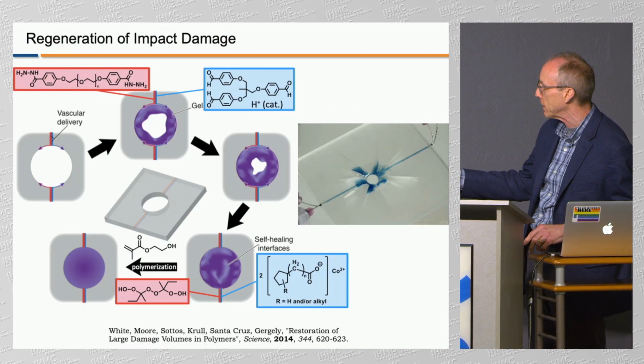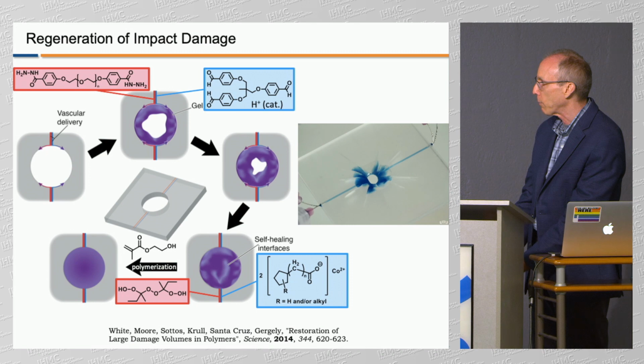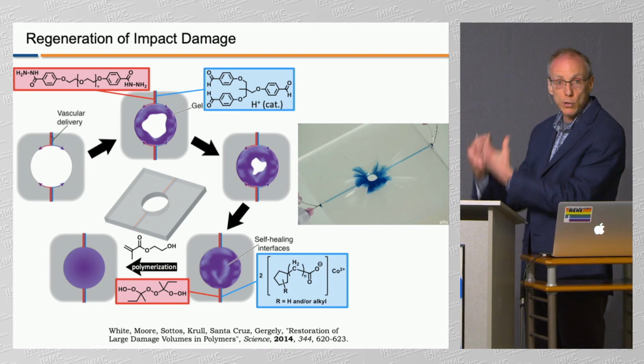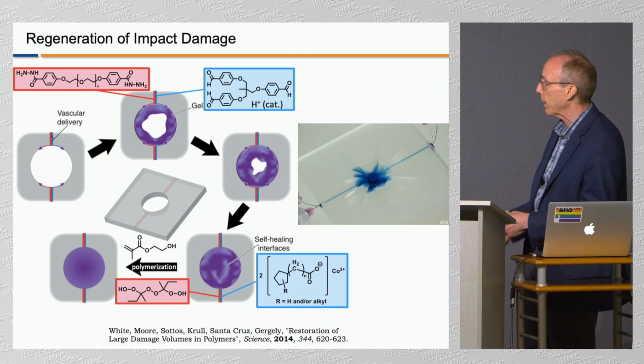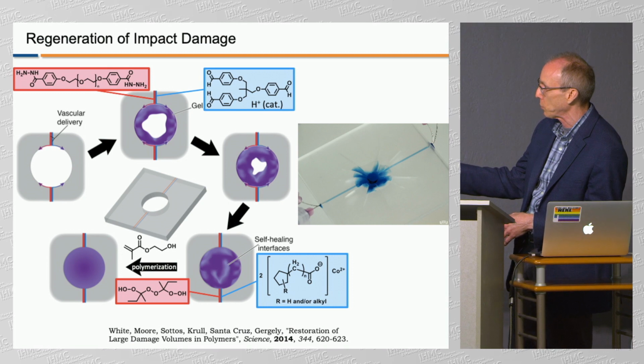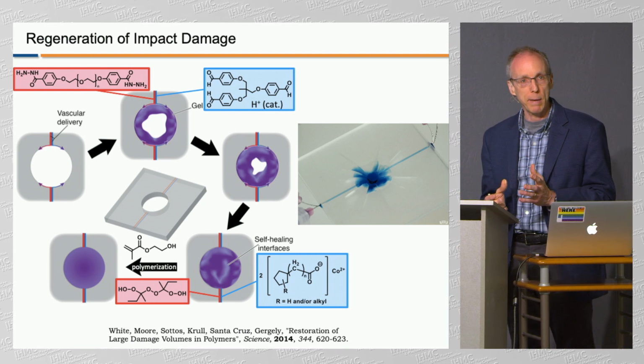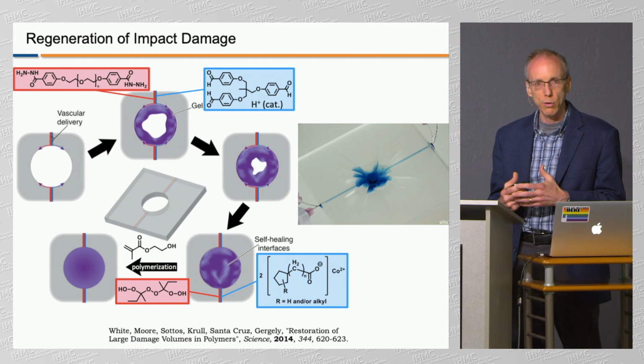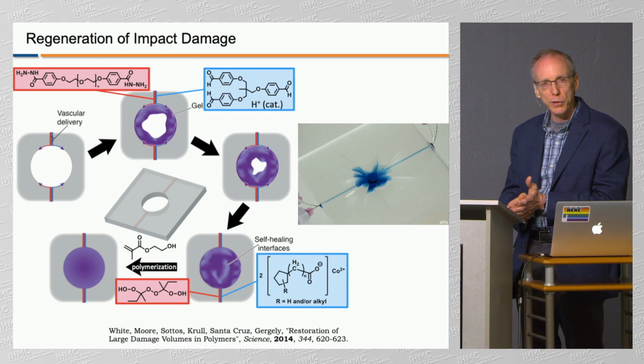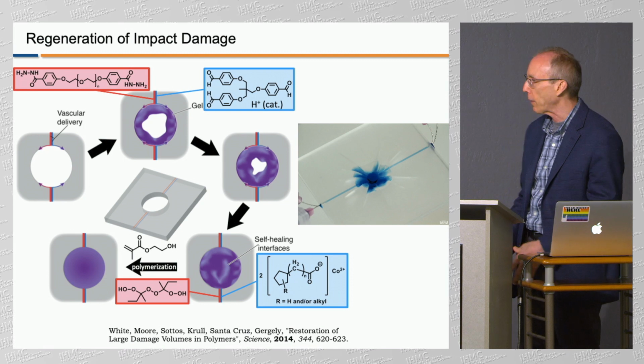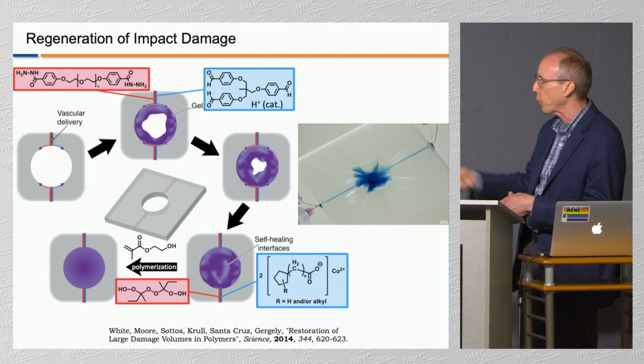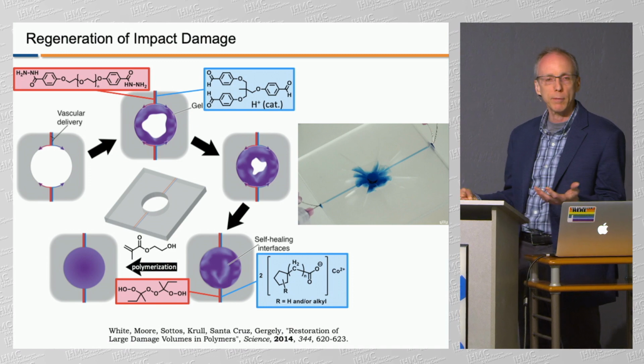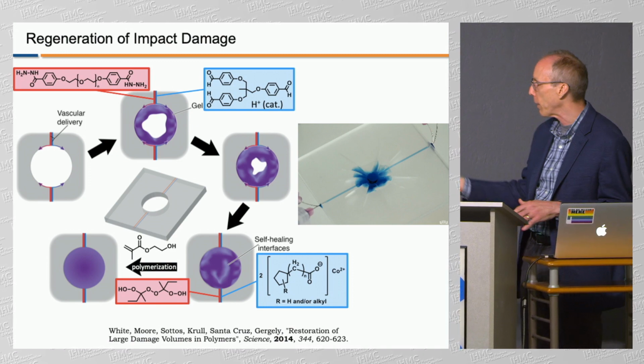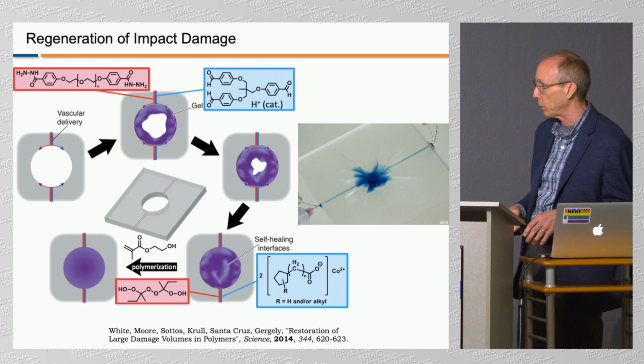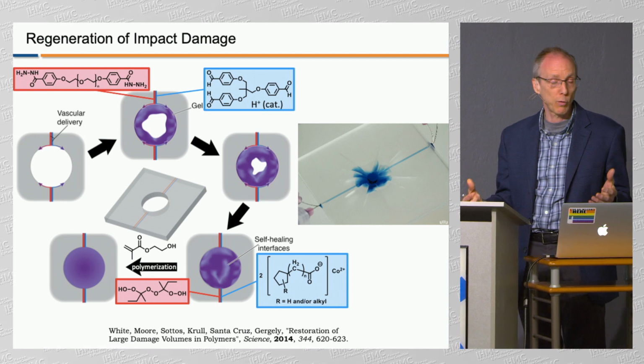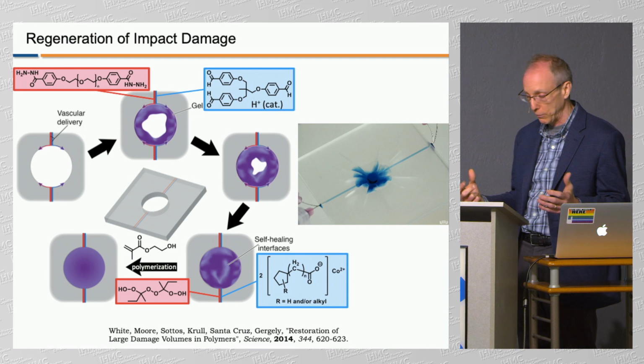Almost to the end, this last idea is really the growth idea. How do you fill a hole that's been damaged without gravity causing these liquids to drip down before the hole is filled? What we invented was some chemistry that first gelled in that space, as a gelatin-like structure that allowed it to fuse together without dripping down. And then finally, once that gel had filled the hole, in time a second polymerization took place to harden that material and restore it to its final form that has the functional properties of the original material.